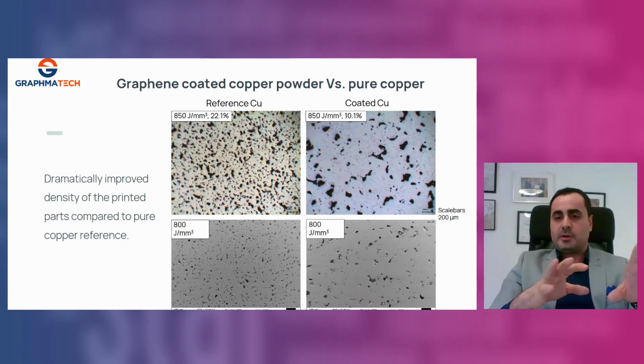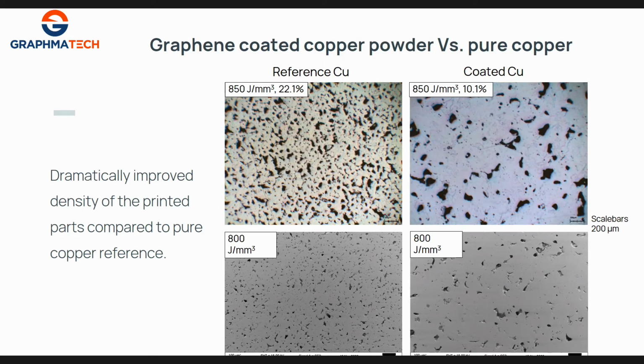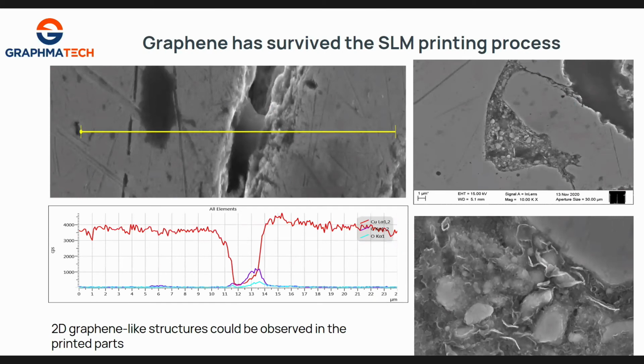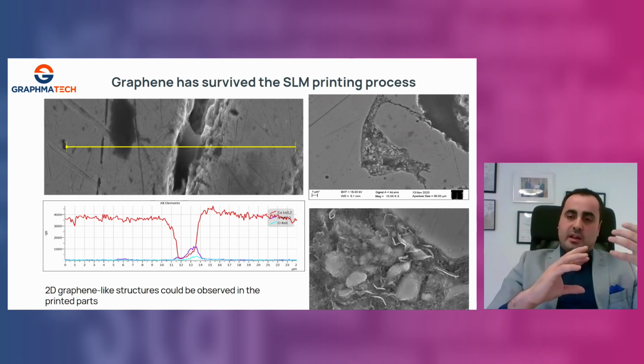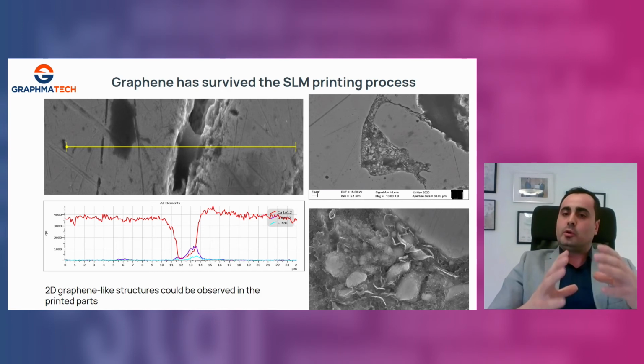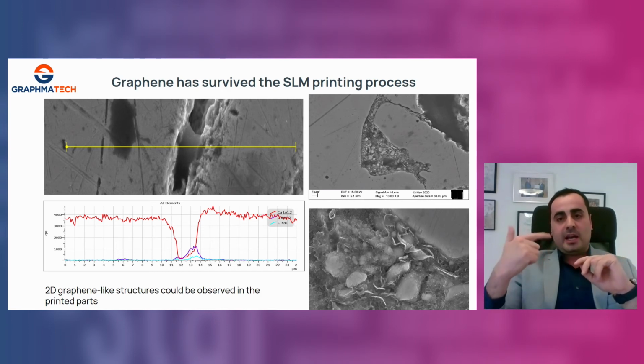Here you can see optical microscopy and scanning electron microscopy of the pure copper reference and the copper coated with graphene. And what we have observed is that the density of the coated copper with graphene has been much better than the density of the pure copper. And okay, that's an extremely good indication. And what was even more interesting is that the graphene has survived the 3D printing. We could detect, as you can see here, a sheet-like structure in the material, which is similar to the starting graphene material and the coating process. This is super interesting because we already improved the processability of copper, but there is also a strong indication that the graphene has survived to further improve the characteristics of the component. So here the improvement is at two levels. It's at the powder and at the component, and this combination is what makes the business case very interesting.